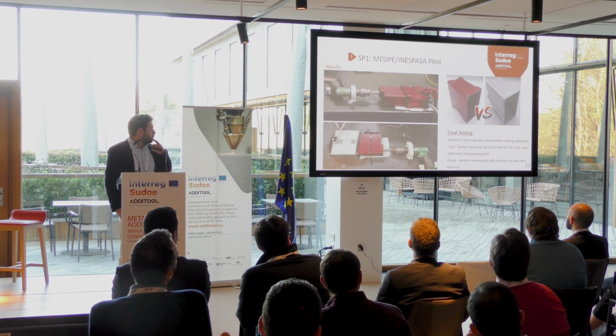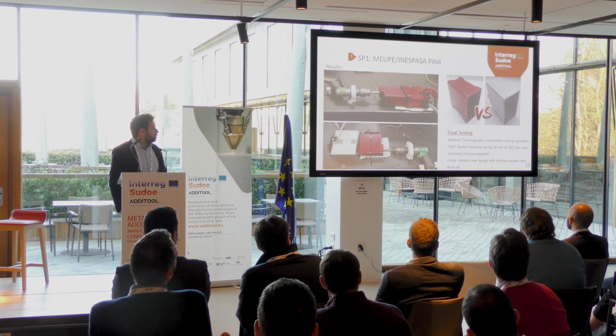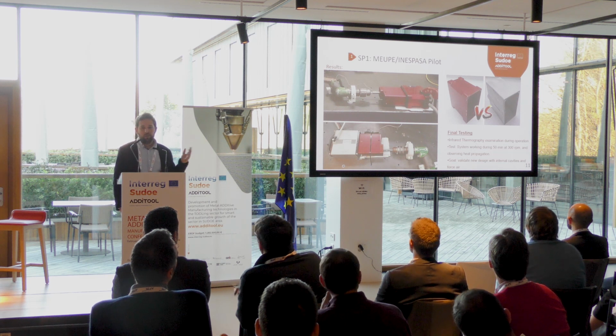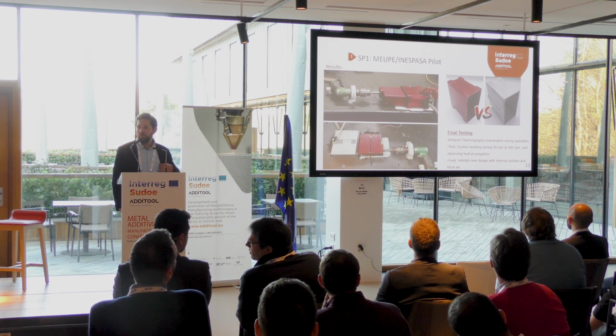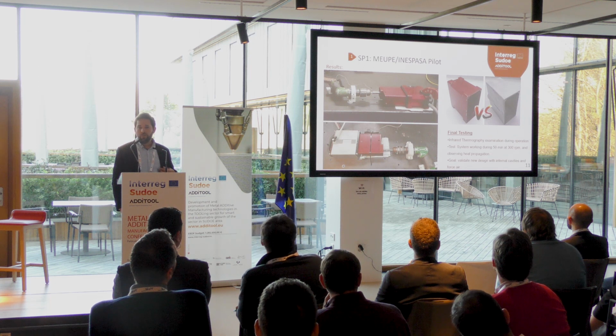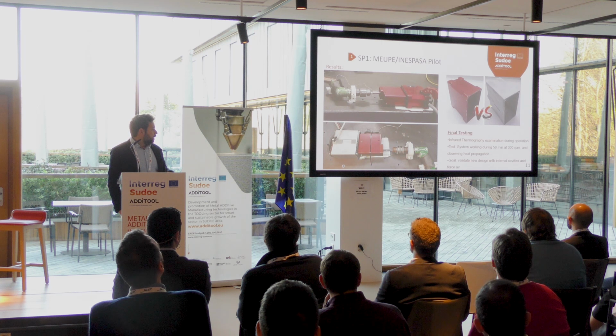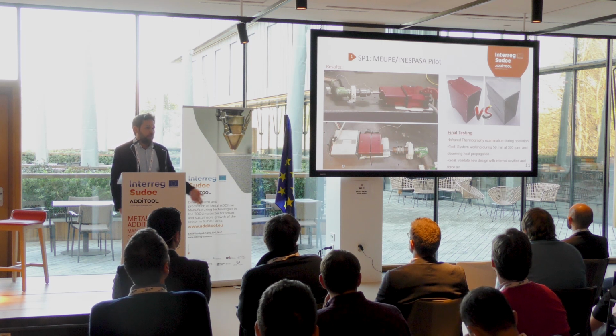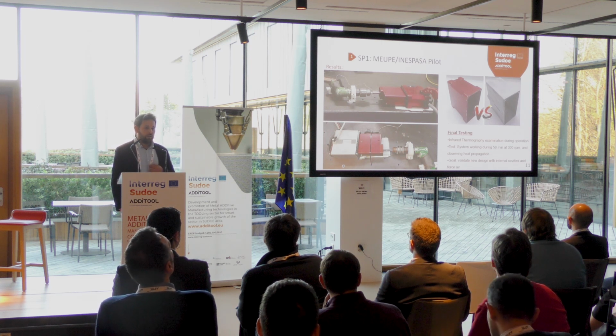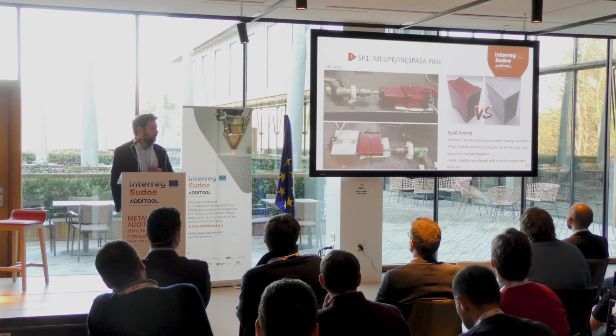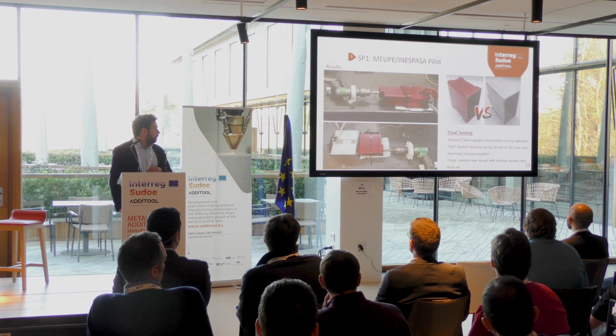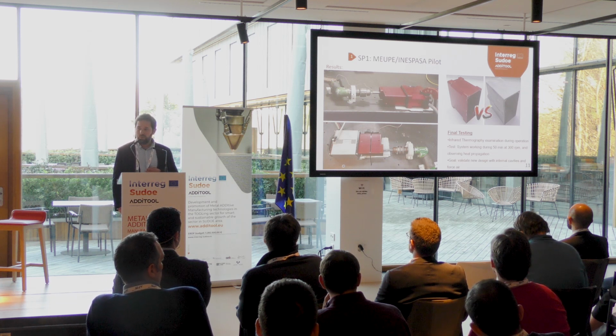We wanted to compare both solutions, testing in the same range. We put it working through 300 revolutions per minute during 15 minutes, and we use, again, thermocouples and infrared thermography camera to monitor the heat propagation of both solutions.